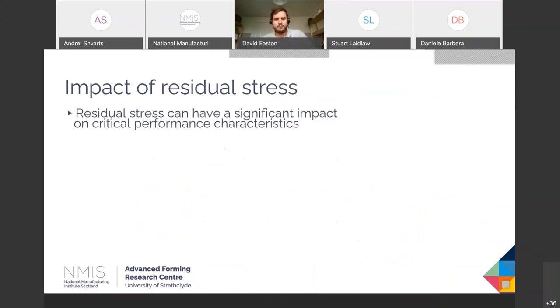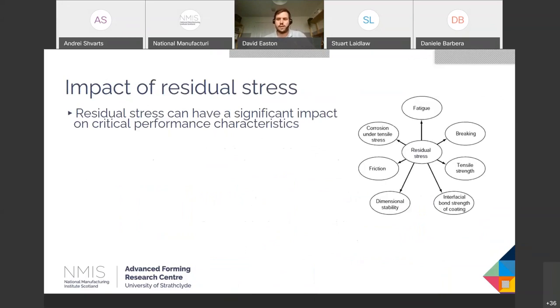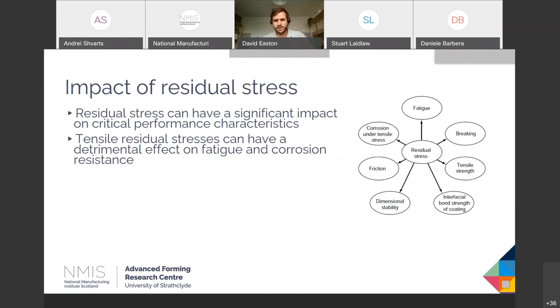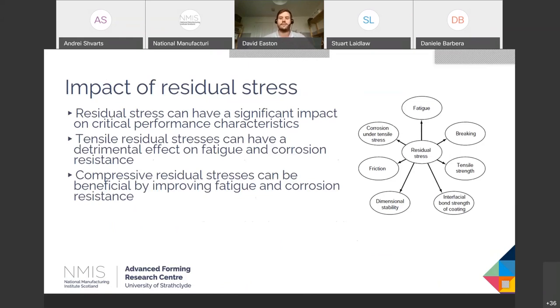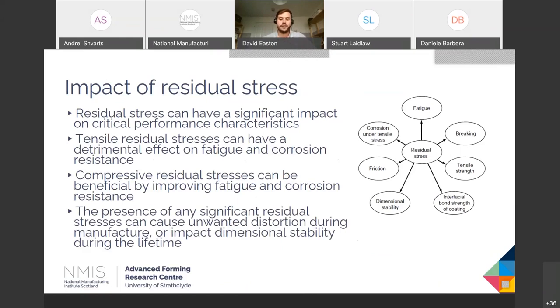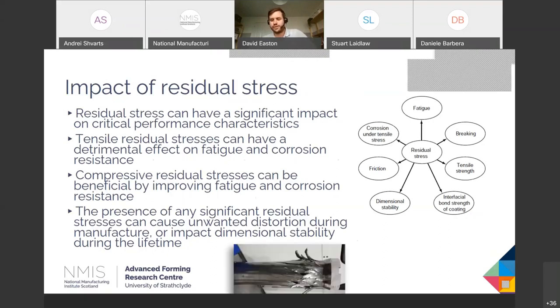Well, it has a significant impact on many different critical performance characteristics. We can see here in the diagram just some of them listed, and fatigue being an obvious one, corrosion, fracture, tensile strength, dimensional stability. It really can have a part to play in a lot of these material characteristics. Tensile stresses, of course, can have a detrimental effect on fatigue and corrosion. Compressive can be conversely beneficial. Any residual stress, whether you want it there or you don't, whether it's tensile, whether it's compressive, can cause distortion during manufacture, whether this is during machining or whether it's a change in the dimensional stability during the lifetime of the part.